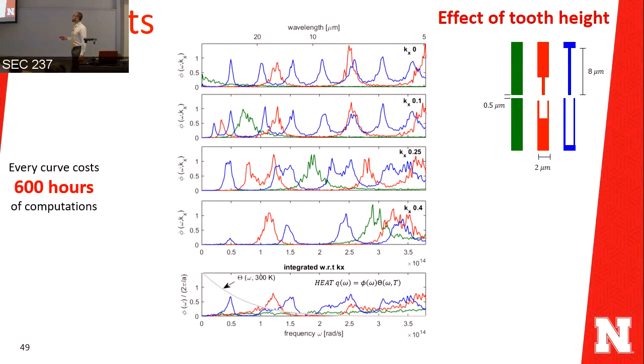You can notice here the flat surface has the green curve. It almost has no peaks. It just has one peak here, one peak here. At the relevant frequencies, it does not even exist at high values of wave vector. Introducing a short tooth will bring some peaks to the transmission factor, and the deeper the tooth, the more peaks you can introduce, at very high values of wave vector and low frequencies.